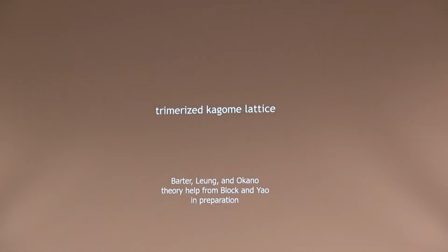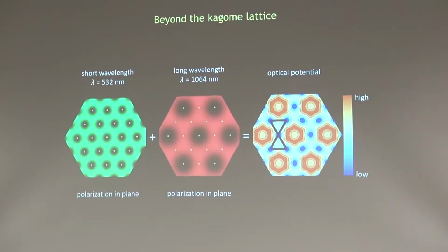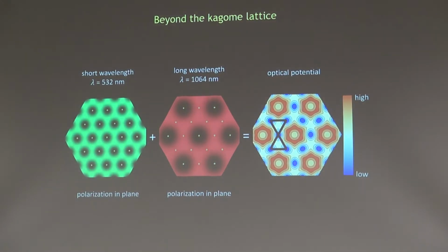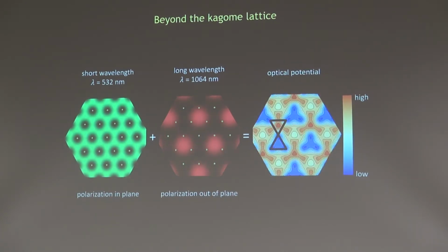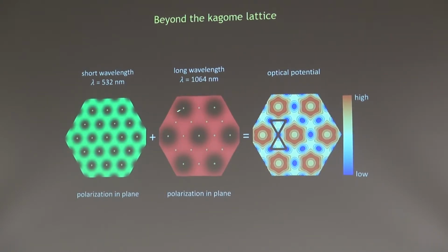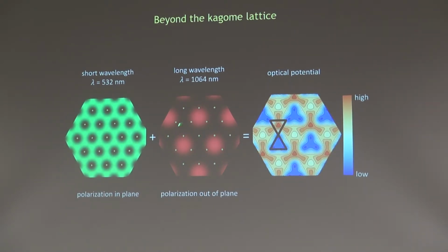Okay, great. So now let's expand even further the kind of lattices that we can treat in our quantum simulators. A student, Tom Barter, pointed this out as he was trying to figure out the next experiment to do in the lab: simply by rotating the polarization of one of our lattice beams in this configuration, we could produce a rather different kind of Kagome lattice. So now when we rotate the polarization of the infrared light, in particular out of plane, we go from a triangular lattice of 0 intensities to a triangular lattice of maximum intensities. So now the infrared lattice presents a triangular pattern where the potential is deepened.